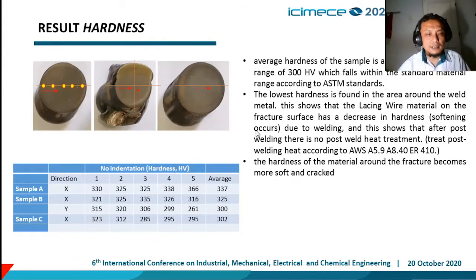So this is the hardness test. We take 5 points in the X and Y directions. The average hardness of the sample is almost the same, about 300, which falls within the standard material range according to the ASTM standard. The lowest hardness is found in the area around the weld metal. This shows that the Lacing Wire material on the fracture surface has decreased in hardness due to welding, and this shows that after welding there was no post-weld heat treatment.